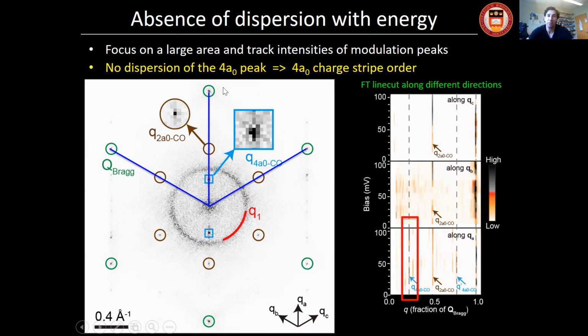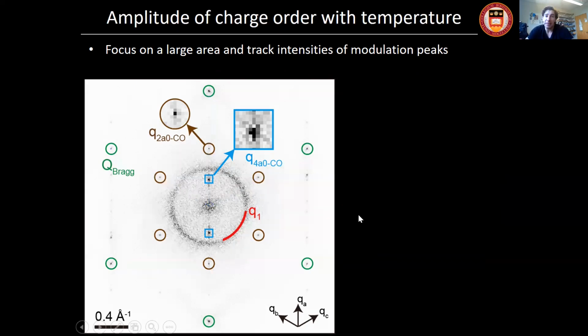So this lack of dispersion of the 4A0 peak necessarily signals the existence of a 4A0 charge ordering of some sort. Given the fact that it exists along one direction, we can call it a unidirectional charge order, or charge stripe order, if you will. Given that it exists at low temperature, we wanted to carefully map it and see at what point it disappears. That was very important just to confirm that this is not some kind of surface reconstruction.